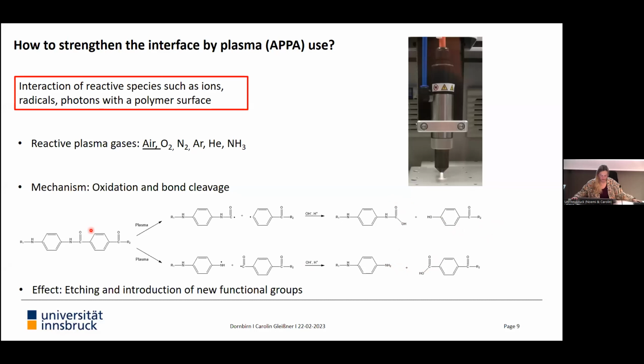And this is an aramid now, but if you have, for instance, a polyamide 6,6 chain, then you have an aliphatic part here, where also new functional groups can be formed. And from literature, it's also known that an etching will occur, because as you can see, you also have a chain scission here.